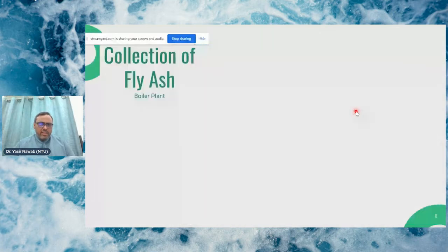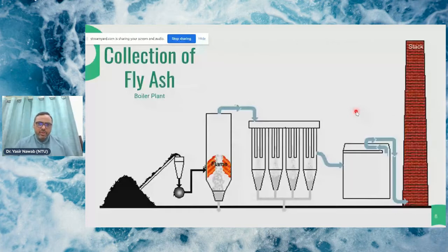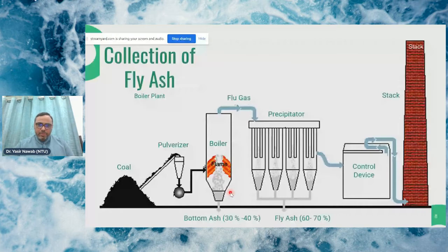So in textiles, the major source are the boilers. In Pakistan, we have a lot of boilers. You can say the number is between 6,000 to 8,000 boilers, and most of them use coal or the rags. And then the second source is brick kilns. So when we use coal at the point of flame, again we have a bottom ash. It's about 30 to 40%, and then collection in the precipitators or the filter is about 60 to 70%.